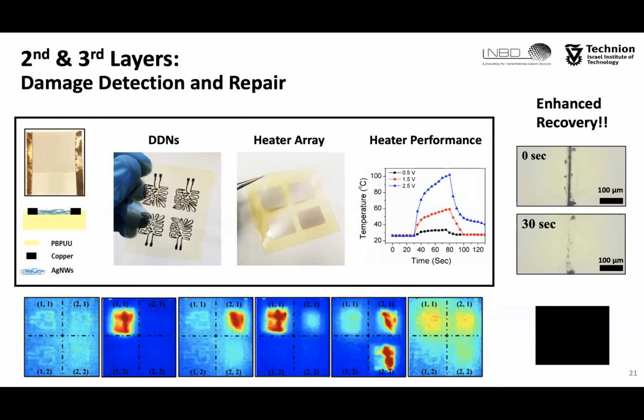With this design, we could achieve accelerated recovery of the detectable damaged parts by integration of an array of self-healing electrical heaters that apply local heat to the damaged areas, leading to very efficient acceleration of repair.